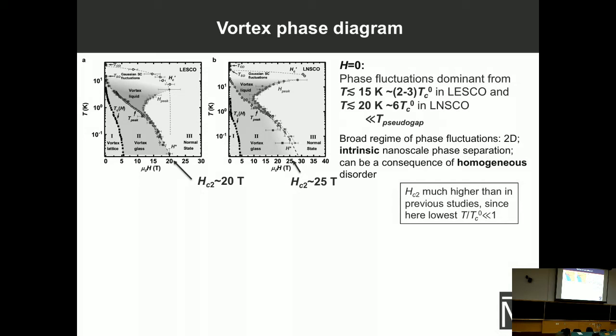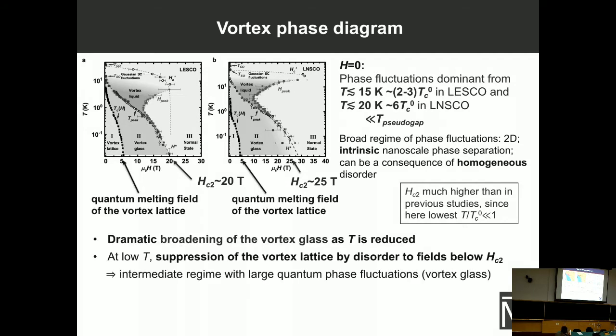I also note that the values that we found are much higher than in previous studies. For example, for this material, it was claimed that the upper critical field was less than 8 Tesla, but that study, as I said, was done at much higher temperatures. So that field basically corresponds to this change from the vortex glass to vortex liquid regime, non-ohmic to ohmic. So this really underlines the importance of going to lower temperatures, because we can see from the phase diagrams that this vortex glass regime broadens significantly as the temperature is reduced. And we attribute this to the effects of disorder at very low temperatures, which melts this vortex solid into this vortex glass regime.